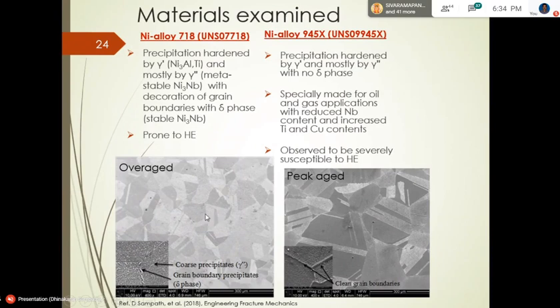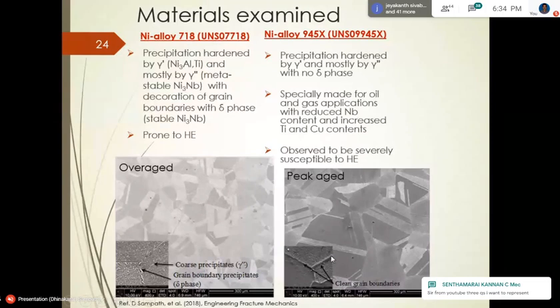But still, this is a softer matrix. That's the reason why 718 is better than 945X. And 945X is peak-aged, with slightly bigger grains, and they have a large fraction of long twin boundaries. So that is also one reason why we see twin boundary cracking in 945X. Does that answer the question?